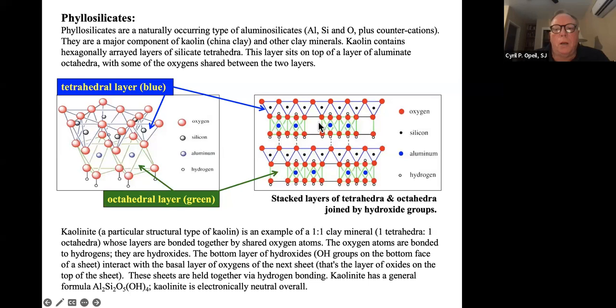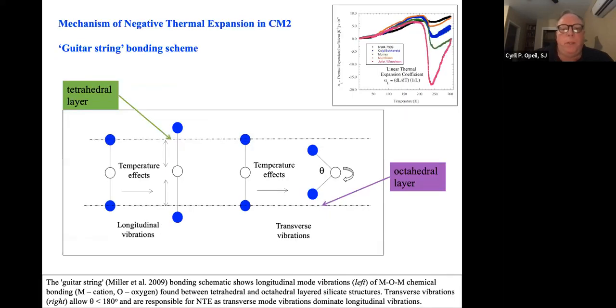And so we have to understand how we have these stacked layers, which are very uniform in a sense. It was actually by looking at the properties of phyllosilicates, or clays, that we were able to understand how this happens. So what's the negative thermal expansion behavior? If we have a tetrahedral layer here and an octahedral layer here, all these atoms, particularly the hydroxyl groups, are bonded from the top to the bottom.